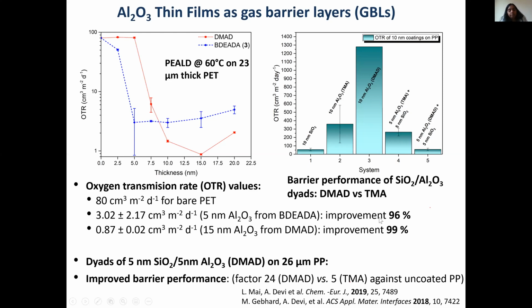And that's quite an impressive result, because you're able to tune the OTR values based on thickness, and with such a small thickness, for example, 5 nanometers, that's nothing, right? So we also tried to make a combination, not just with aluminum oxide. Here you can see SiO2, which in present-day technology is used very effectively as gas barrier layers.